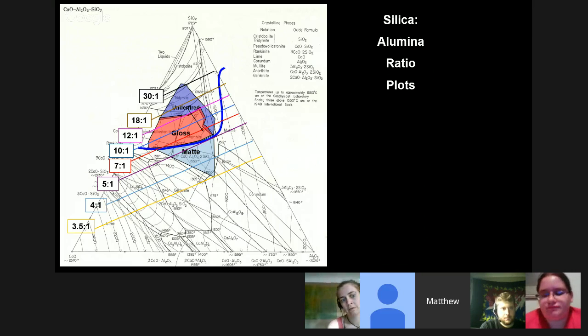That's how crystallization happens. That's the whole act of chemistry: you heat a certain combination of two, three, or four elements, and then on the cooling or somewhere in the heating cycle they form a new material. That's where we end up with the crystallization of these materials, but we can track what stays glass versus what precipitates. So it's this gray area; we're really talking about the glass formation boundary, and it's the stability of the glass that's the major dictating factor, which is why we can get these wollastonite crystallizations.